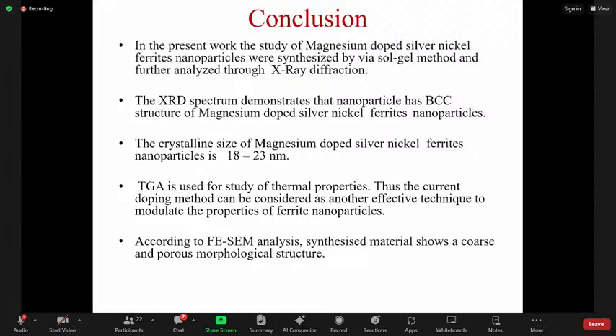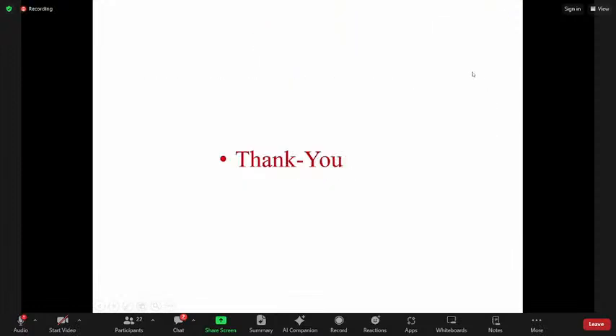Now, I want to conclude my presentation. In the present work, I studied magnesium doped silver nickel ferrite nanoparticles via the sol-gel method. The XRD pattern gives the BCC structure and the crystalline size 18 to 23 nanometers. After that, TGA is studied for the thermal properties. And by SEM, I got the morphological structure. Yes, there are some applications of my synthesized product in antimicrobial and photocatalytic reactions. So these are some references and I would like to thank you for giving such a chance.